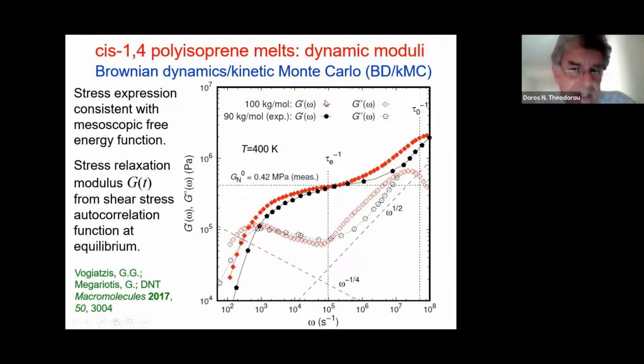So we can get these properties from the mesoscopic simulation. First of all, we get the stress relaxation modulus from the time autocorrelation function of the shear stress. And then we Fourier transform it, and we get G prime and G double prime. And here they are from the mesoscopic simulations with the red points. The G prime is the filled red points, the G double prime is the open red points.